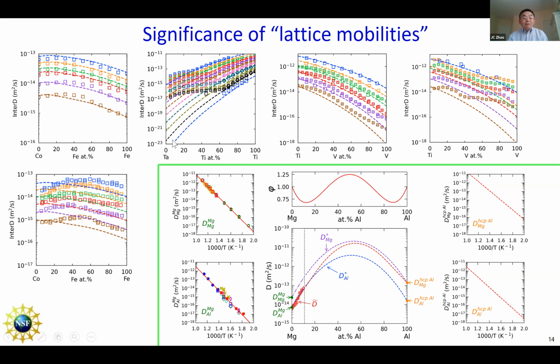And then, if you have very reliable data, in this case we get a very nice data of titanium in tantalum, the impurity diffusion coefficient at this temperature is here. Instead, the experimental data is extrapolating into a much, much higher value, orders of magnitude higher. And this is not very reliable. When this could bend over, you can see that kind of phenomenon. In that case, you need to kick out those data. Otherwise, you're going to get very wrong results, because it has to agree on both sides with the impurity diffusion coefficient, as I mentioned.